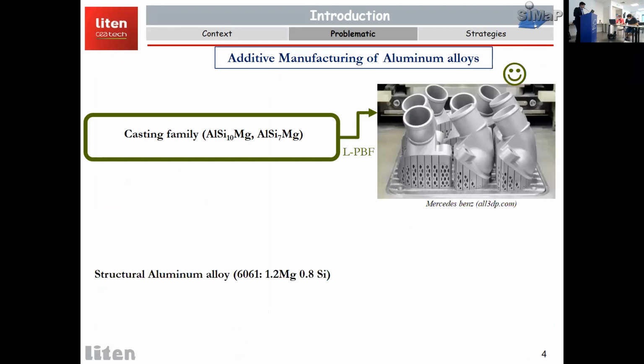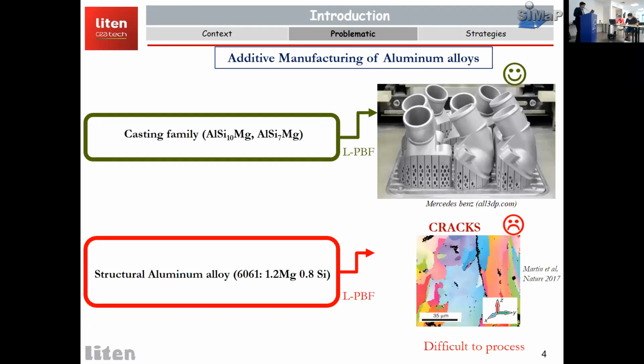If we look into the structural aluminum alloy, for instance, the 6061 aluminum alloy, which has magnesium and silicon as its major alloying elements. If we do the L-PBF of structural aluminum alloys, we tend to get a lot of cracks, and it's very difficult to process.